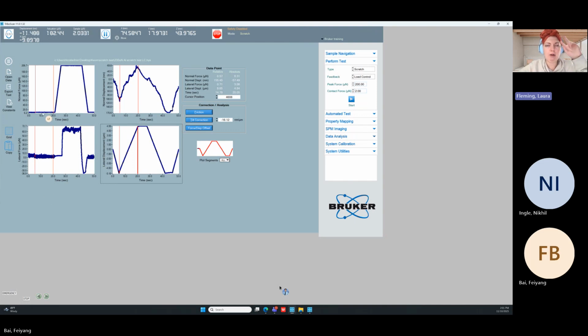So that tells me what segment I'm looking at. During that segment, my normal force was 0, so I was lightly tracing along the sample surface. And then we also have this lateral displacement from -5 to +5. Looking at the normal displacement, I can see the relative difference there is 155 nanometers, which is significant and not what we want to see. That's the tilt, and I'd like to take the tilt out of the equation.